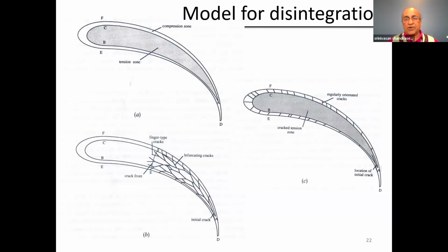So usually the velocities will drop, and in a few cases we have actually measured the velocities in the compression zone. It's much lower, on the order of a couple of 100 meters per second, and then what you saw as fragments flying out, they are only at 25 meters per second. Remember, that is a fragment velocity. What we were talking about at high speeds is the crack velocity.